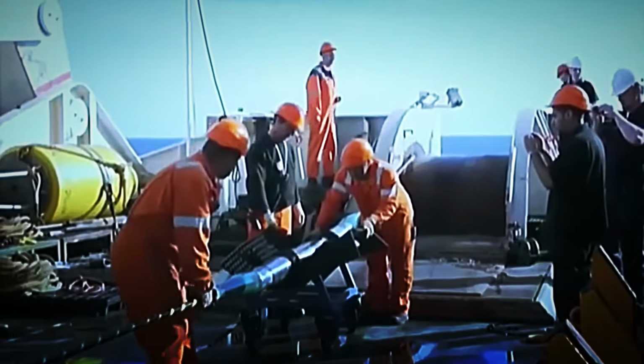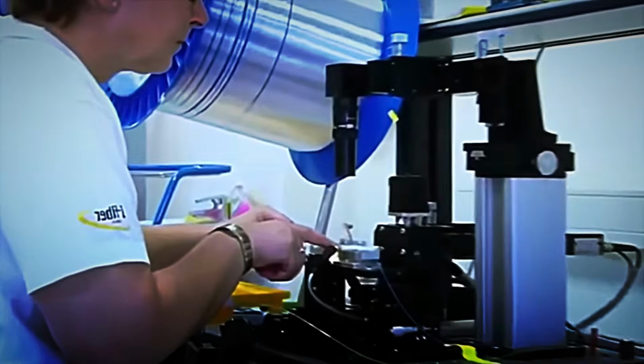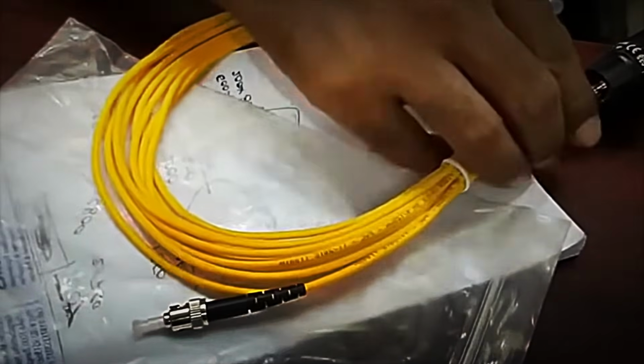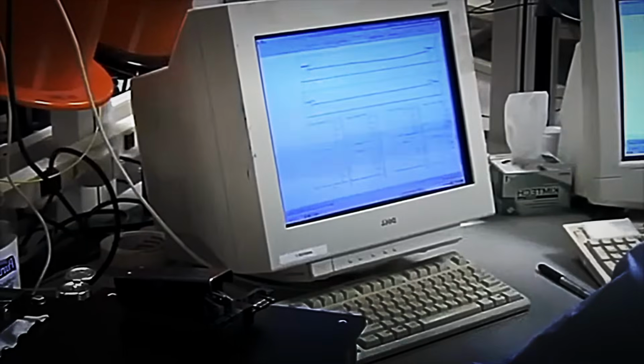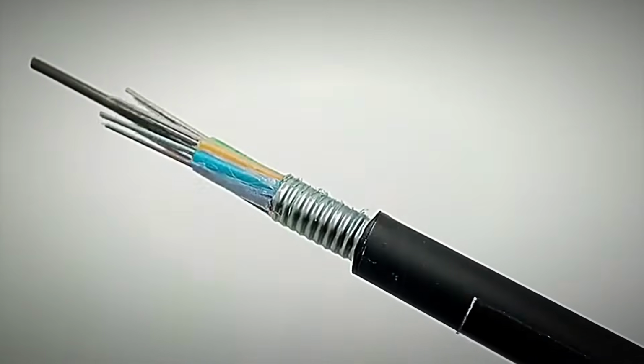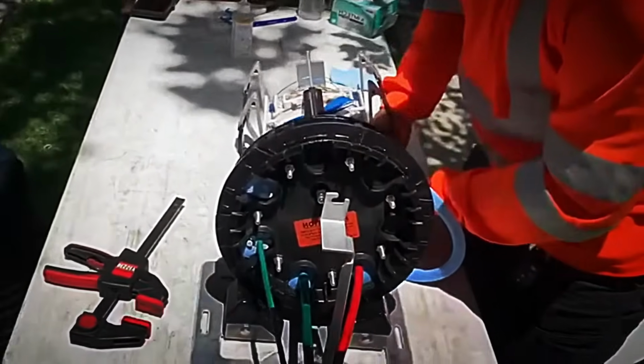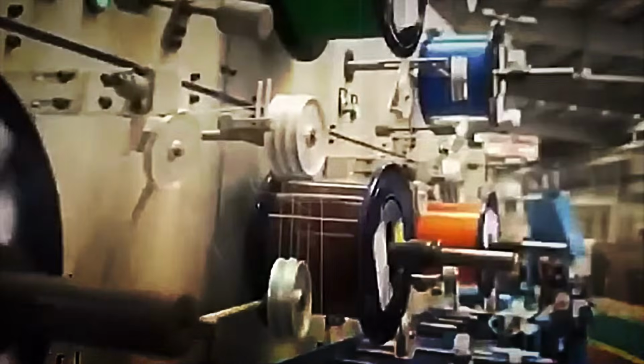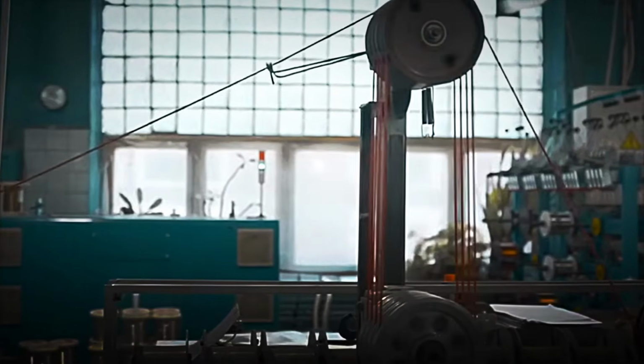The second evaluation is mechanical. Lengths of fiber are placed in tensile testing machines that apply tensions equivalent to several kilograms of force. The aim is to verify that the fiber can withstand the tension it will be subjected to when installed in land or submarine networks. If the fiber shows microcracks or does not reach the specified strength, it is rejected. Flexural tests are also performed. The fiber is wound onto reels of very small radii to verify that it does not break or increase attenuation. This is vital because, in practice, the cables must adapt to bends, splices, and irregular paths.